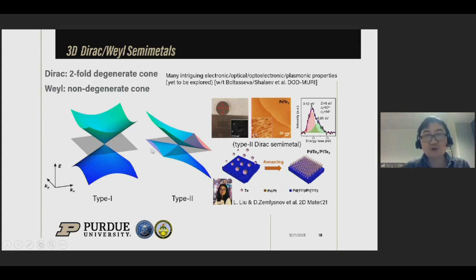Also, in some materials, the Dirac cone can be tilted or even become so-called type 2 with a very large anisotropy and tilted to have a different topology of Fermi surface. In the jargon, some of the relativity-minded people call this Lorentz invariance violating materials. But anyhow, one example of this material was recently synthesized in our laboratory, with this type 2 Dirac fermion dispersion, and potentially with interesting electronic and optoelectronic properties that we're exploring. And this is a part of a new MURI project that we're very excited to start recently, also with Vlad Shalaev and Sasha Boltasseva, looking at a variety of these Dirac Weyl semimetal materials, focusing on their optical, electronic, and plasmonic properties. So